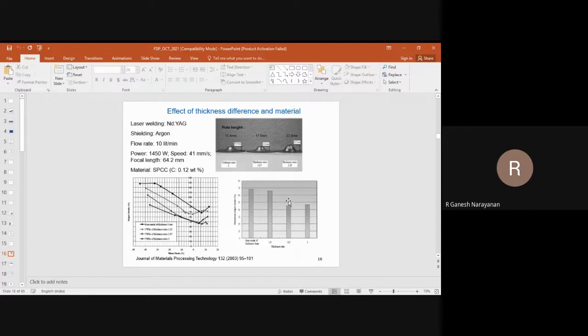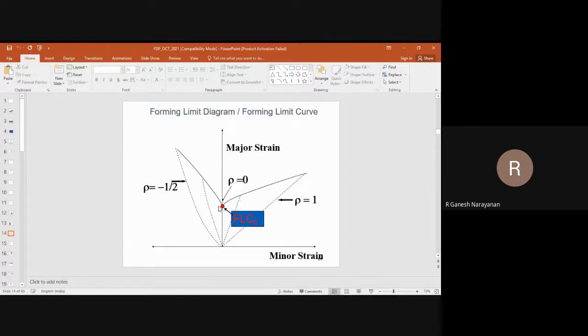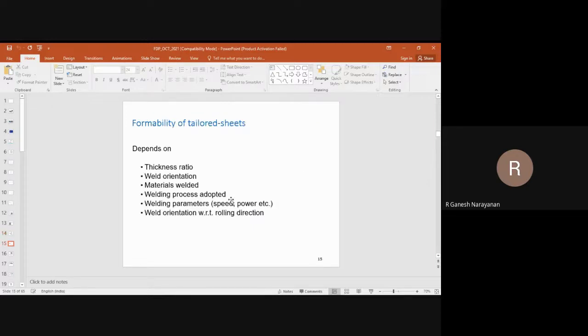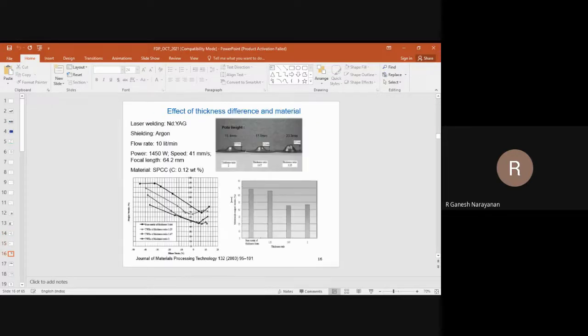Sometimes this lowermost forming limit does not come exactly on the y-axis. It comes a little on the right side or left side. We call that a near plane strain condition, and that can happen for a few reasons. You can see that example here. The minimum is not exactly happening at minor strain being 0. It is slightly away from that. That can happen mainly because of the change in strain path during deformation. But leave out all that. The main idea here is that with the increase in thickness ratio, there are chances of formability coming down, which we do not want.